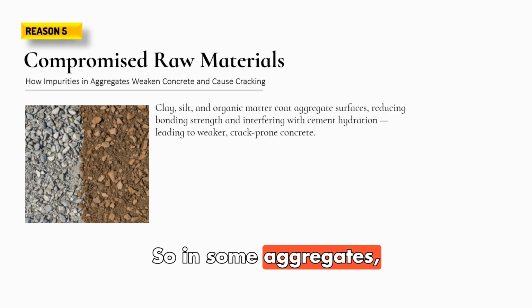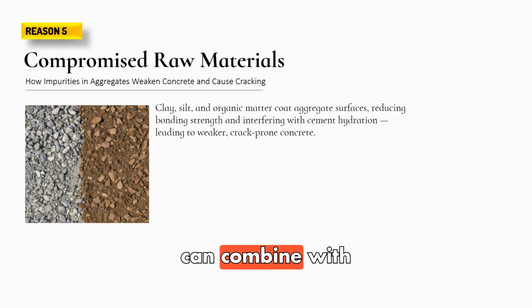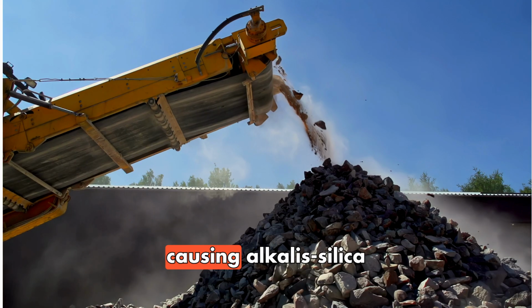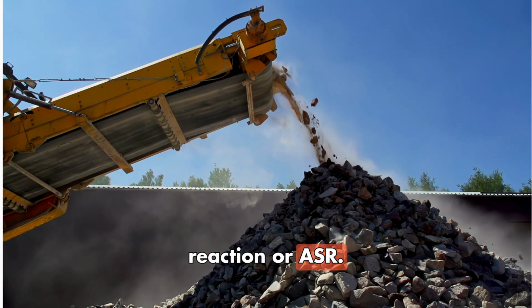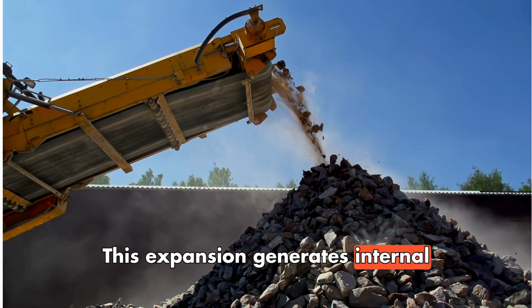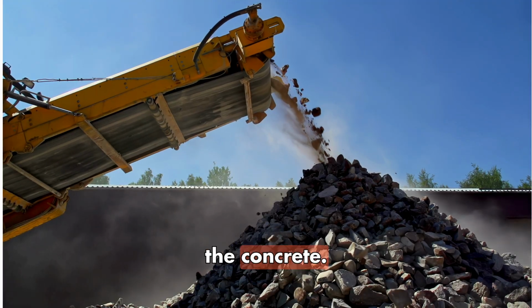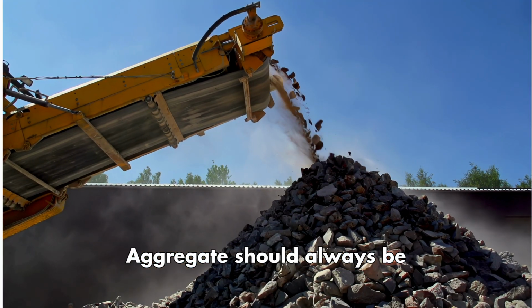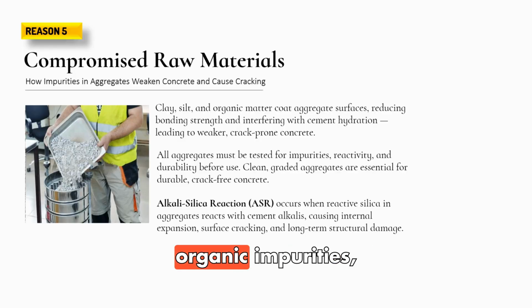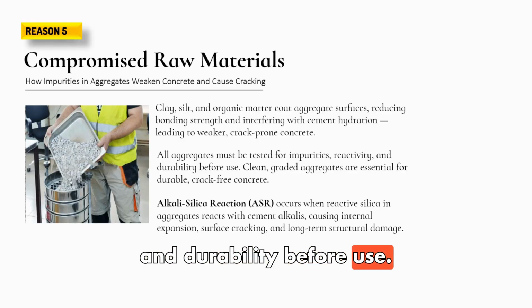In some aggregates, reactive forms of silica can combine with the alkalis in cement, causing alkali-silica reaction, or ASR. This expansion generates internal stresses that eventually crack the concrete. Aggregate should always be tested for silt content, organic impurities, and durability before use.